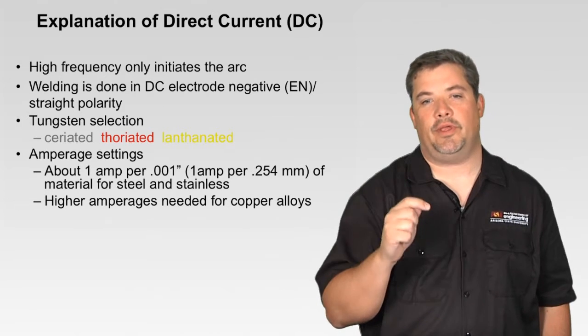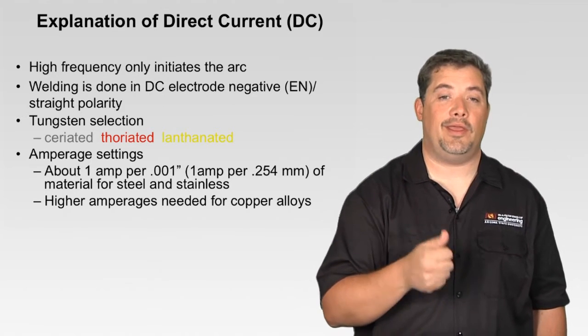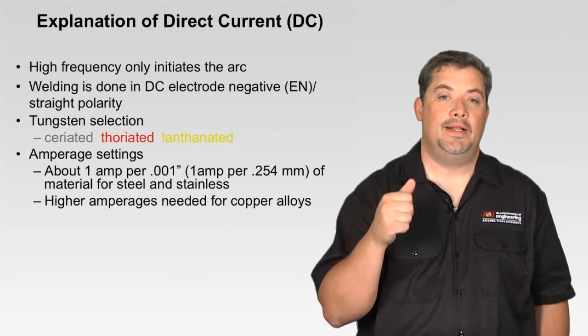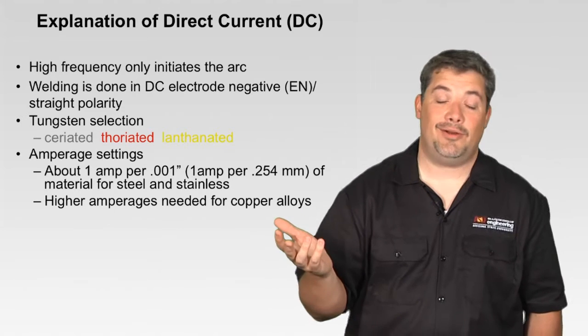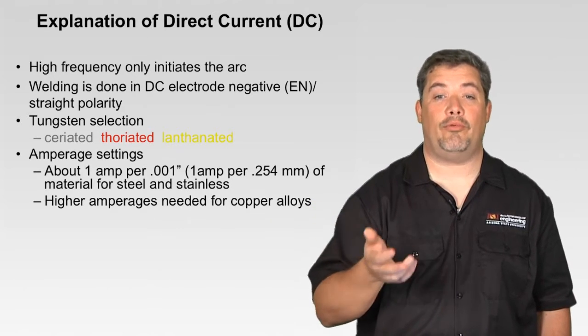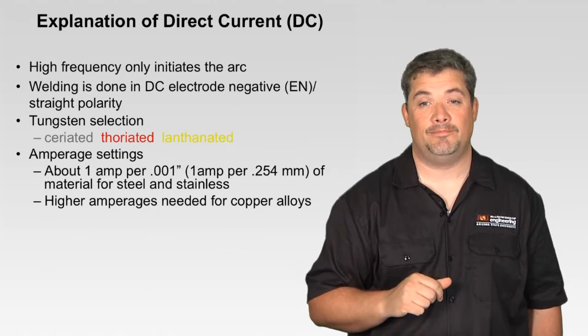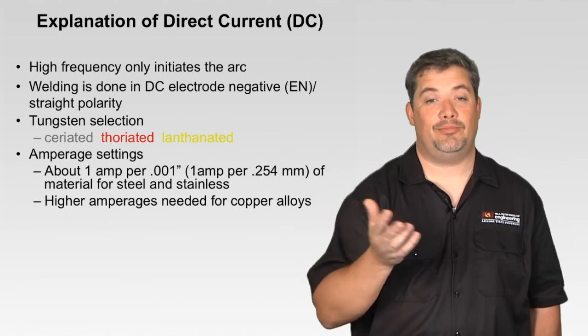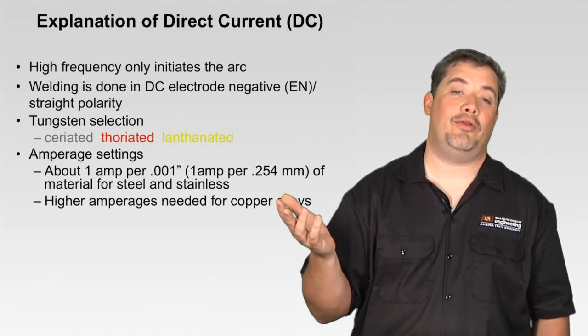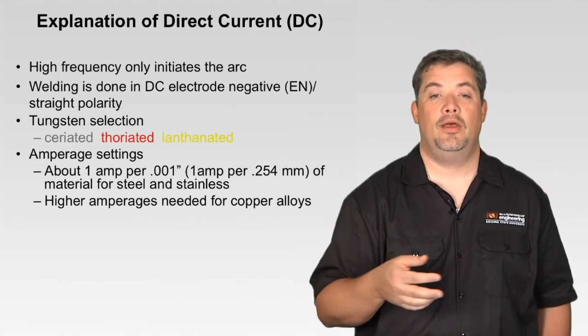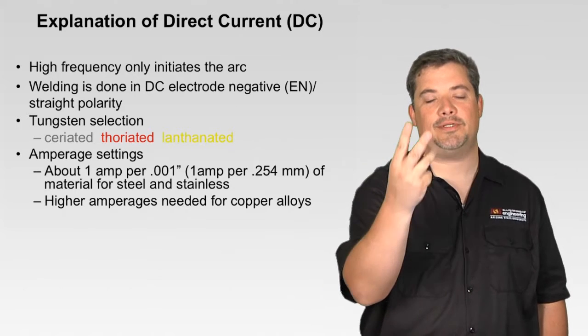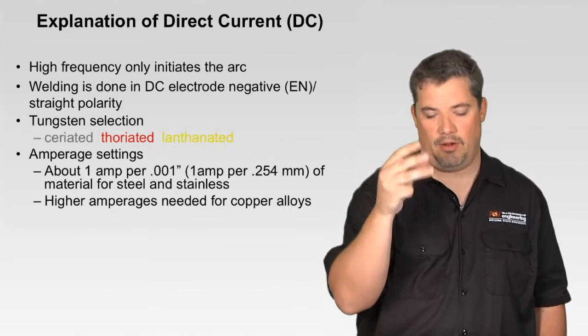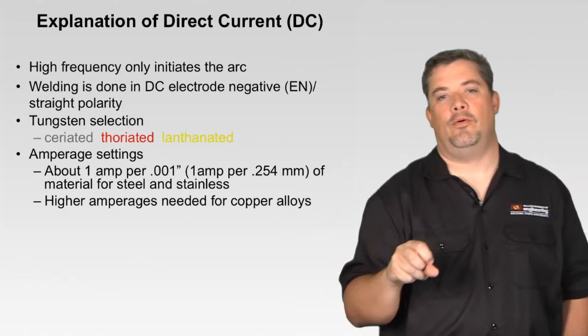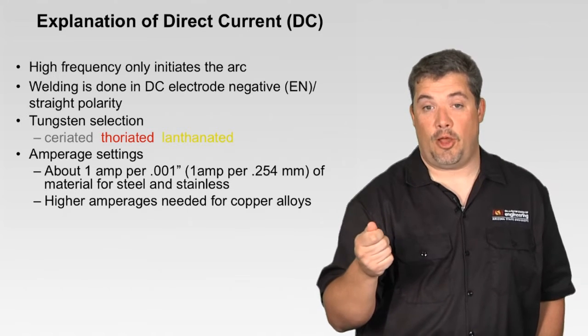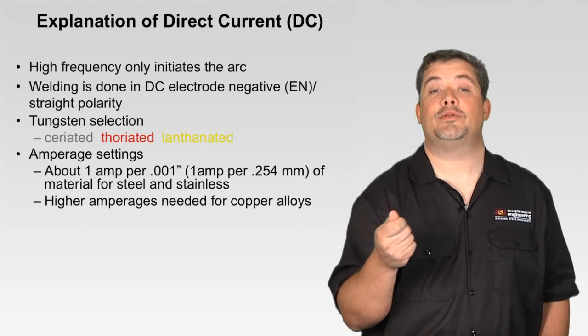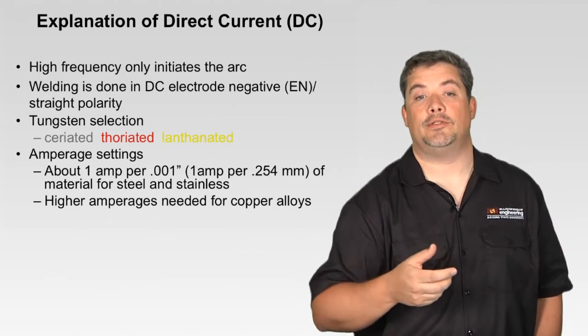So for our tungsten selection, we can use ceriated, lanthanated, and thoriated. Again, ceriated and lanthanated are the best choices. Our amp settings are just like all the other general rules of welding, about 1 amp for every 0.001 inches. Works great. So 1/8 inch, 0.125, roughly 125 amps is going to work to weld 1/8 inch. The key too is volts times amps times time is what melts that puddle. So I can weld at 75 amps a lot slower, or I can weld at 125 amps and go quicker and get the same results.